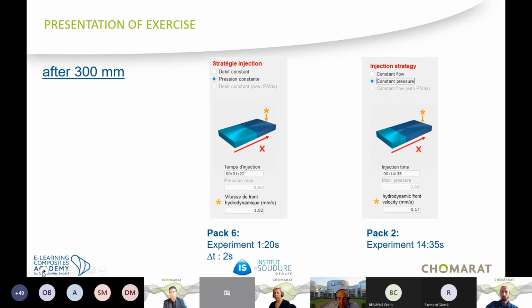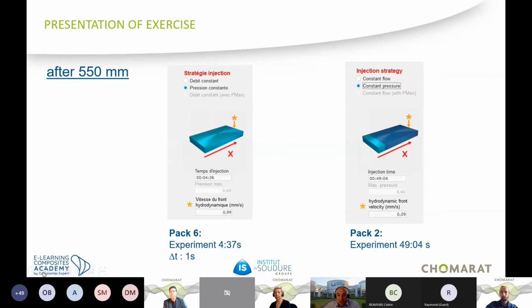The last slide, just after this, will be at the end of the impregnation, because the plate that is provided in the tool is 550 millimeter. So at the end of the impregnation, again, the assessment is very easy. The G-flow provides very fast impregnation, and if we compare the filling time, 4 minutes, again, something like 50 minutes. At the level of the plate, we demonstrate what Vincent just mentioned before, is that using G-flow will provide a big speed in terms of impregnation compared to the use of pure laminate without flow media.